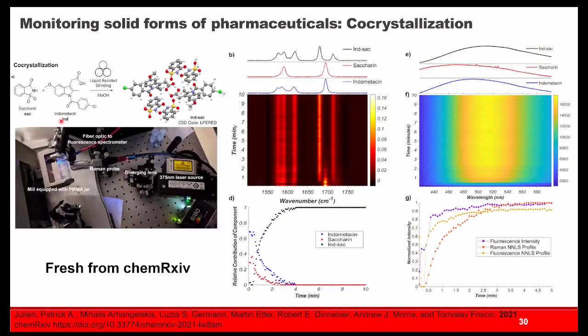One of the more recent projects that I did near the end of my PhD, well, actually throughout my PhD, but it's finally just got posted on ChemRxiv last week, actually, so I'm quite excited to talk about this. Here, we took a pharmaceutical, indomethacin. So this is an API. We're co-crystallizing it with saccharin to make this indomethacin saccharin co-crystal using liquid assisted grinding with methanol.